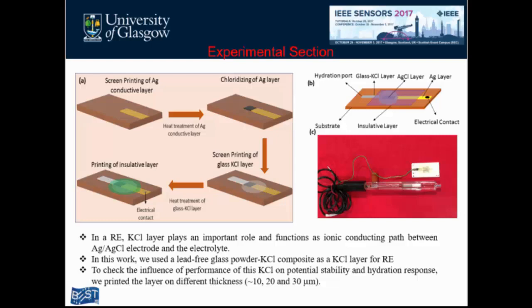Then comes another major task in my work, because a normal reference electrode contains a KCl solution, which is in liquid form. So in thick film technology, we need a thick layer of KCl. The problem with KCl is that it is a salt, and when we make a powder and print it, it will easily dissolve in water. So initially I took this KCl salt and, by a solid state reaction method, by ball milling, made it into a powder. This powder I mixed with a glass composition, again by ball milling, and made a paste. And then I printed this.